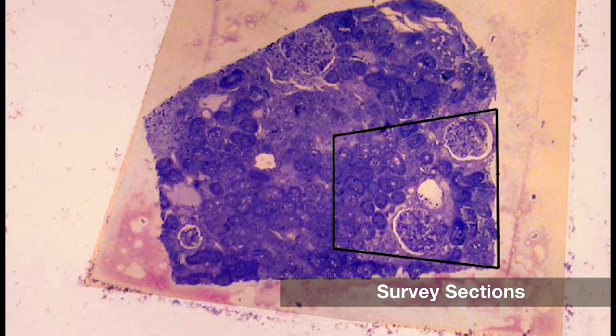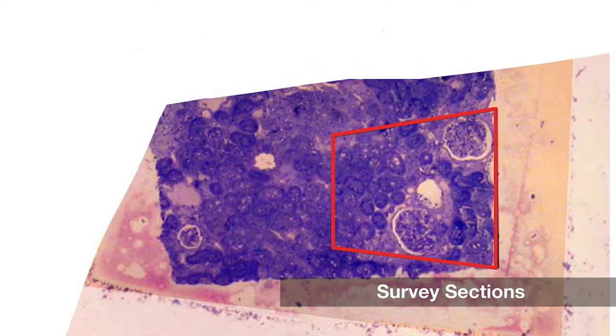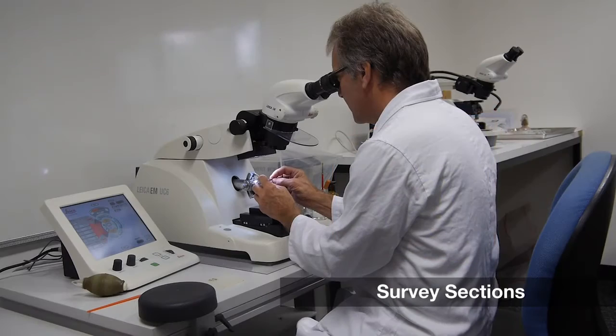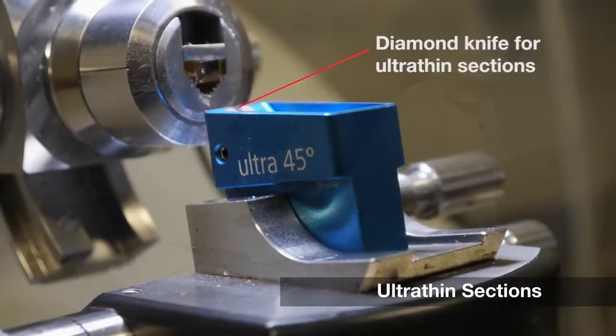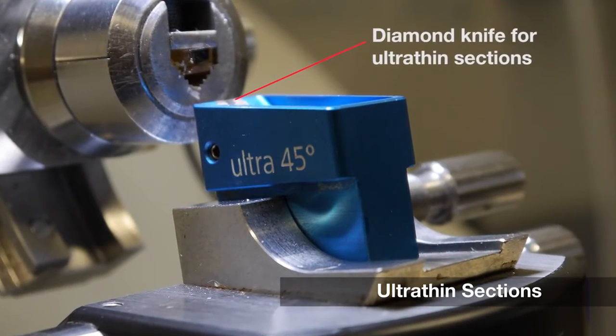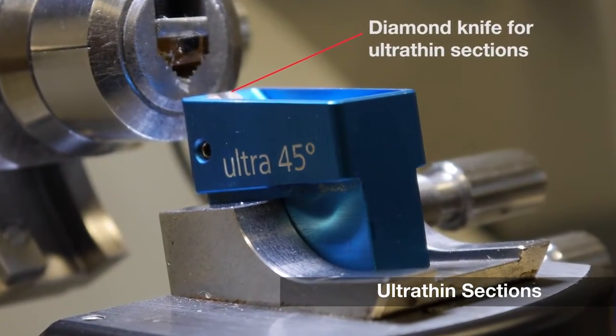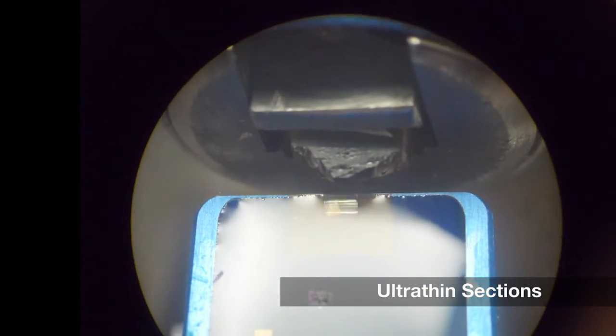Survey sections are too large and too thick to use in the electron microscope. Hence the block is retrimmed to reduce the area of the cutting face. The retrimmed block is returned to the ultramicrotome and realigned. The glass knife is replaced with a diamond knife that makes cutting the ultra-thin sections easier. The water bath is filled with water and the ultra-thin sections float off as they leave the knife edge.